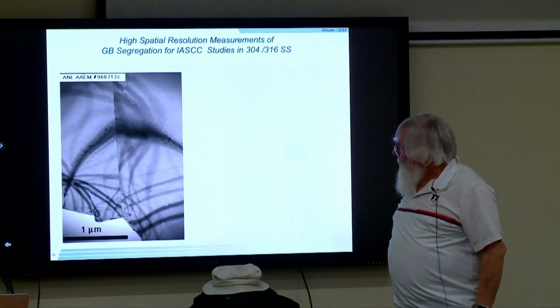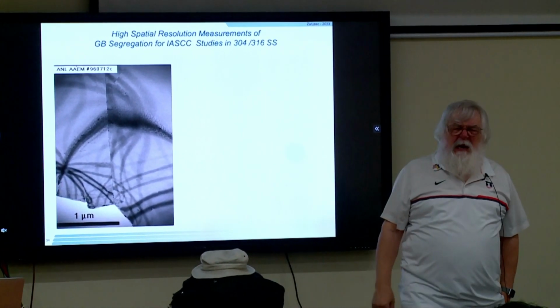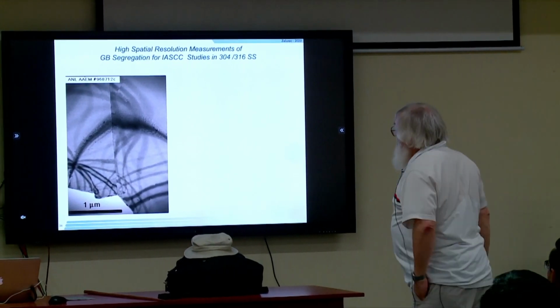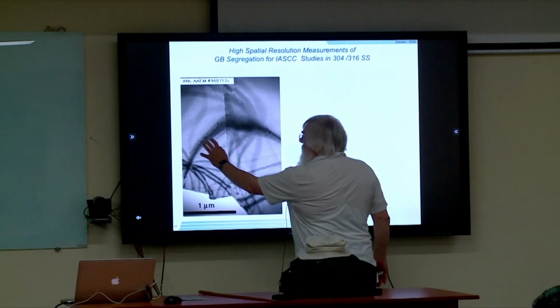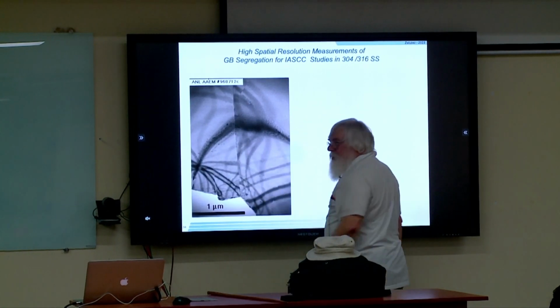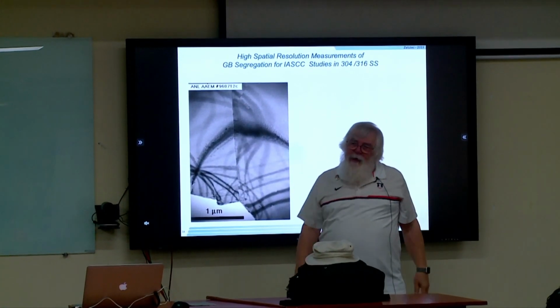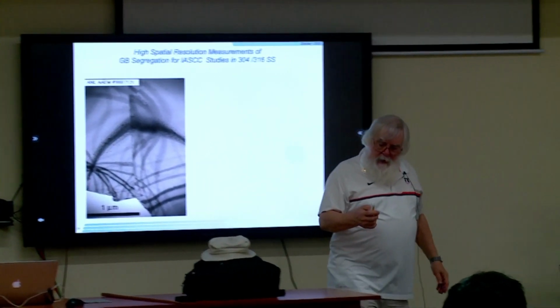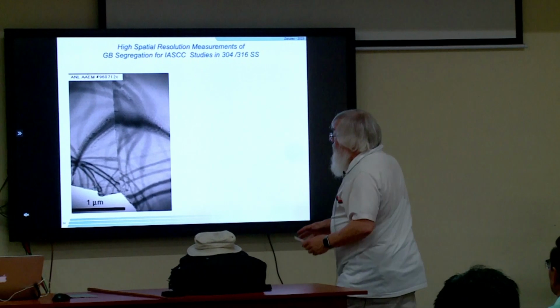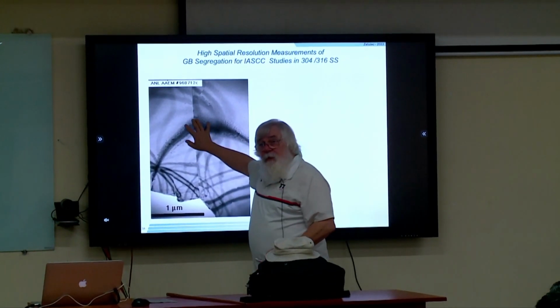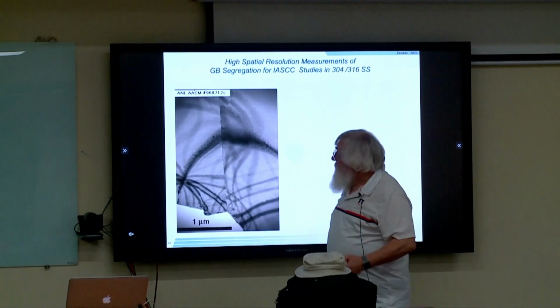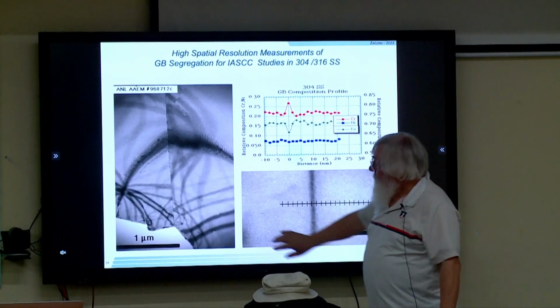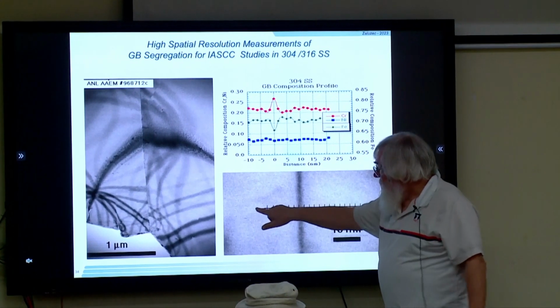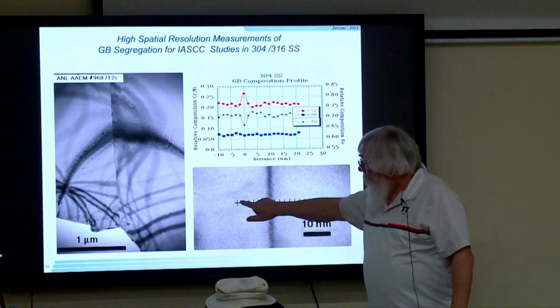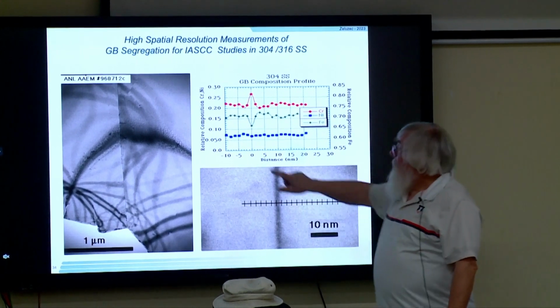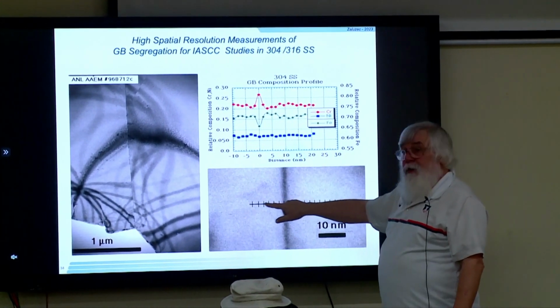Well, we can form an image, and there's nothing really outstanding about that image, right? There's a grain here and a grain here, and there's our grain boundary. What's special about that grain boundary? Why does this grain boundary break and other ones not? That's where we need more than just the elastic image, which is what this is. We're going to go to the inelastic scattering spectroscopies. We're going to go to that grain boundary, blow it up a little bit, and take my electron probe and walk across that grain boundary and measure the composition across it.